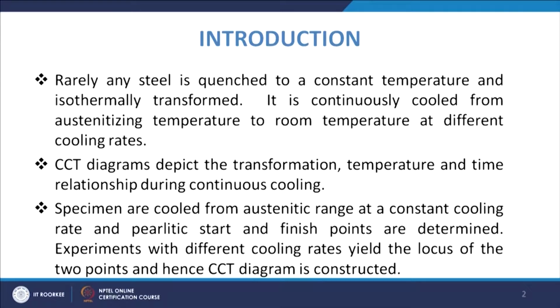So, certainly when you are cooling, you will have different cooling rates from the austenitizing temperature to the room temperature. If you have to take this continuous cooling case into account, these CCT diagrams will be helpful. CCT diagrams depict the transformation temperature and time relationship during continuous cooling, because that is the normal case, and you need to understand how the transformation is going to proceed.